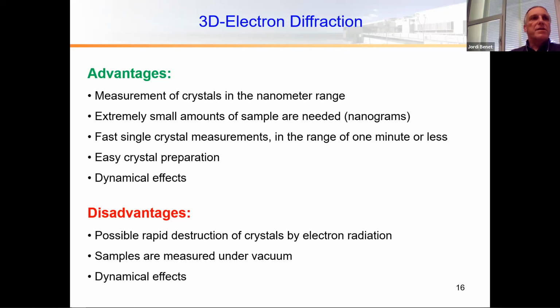As disadvantages, I see a possible rapid destruction of the crystals by electron radiation, that samples are measured under vacuum, and also a disadvantage are the dynamical effects. So you see they are in both positions, and I will explain why they are in both positions in the next slides.